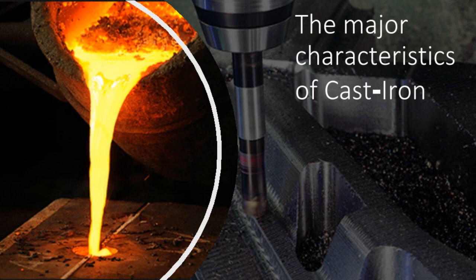After machining cast iron for a few hours, you will find a fine layer of dust on your machine, and your hands will be black from contact with the graphite dust. Cast iron is generally easy to machine, due to the dampening and lubricating properties. Although the cutting speed you use should be lower than you would use for medium carbon steel, cutting tool wear can be caused by pockets of sand, and hard spots where part of the casting may have been cooled quickly.